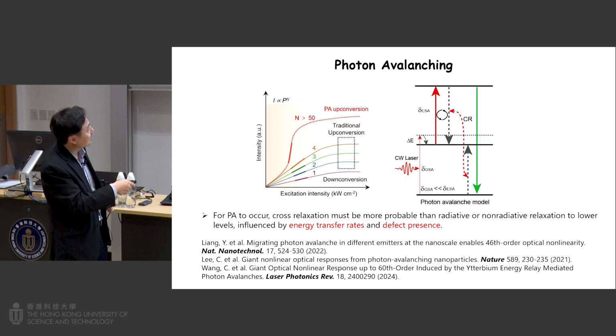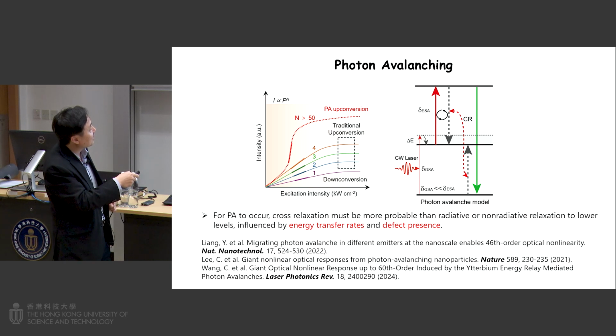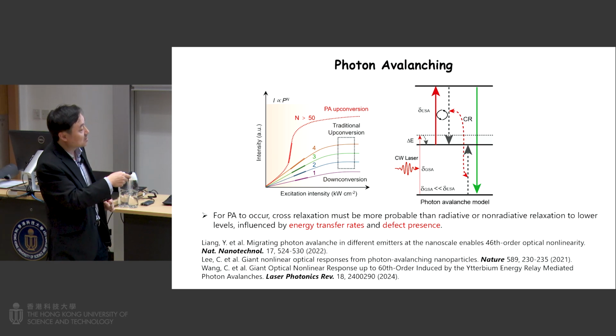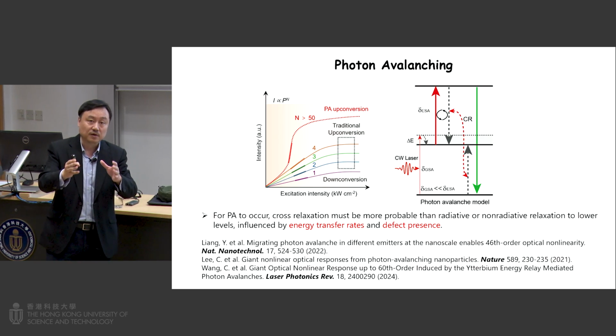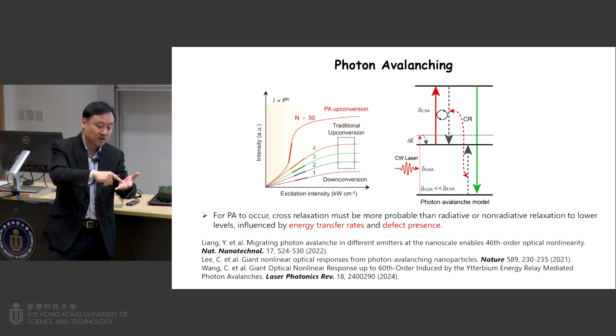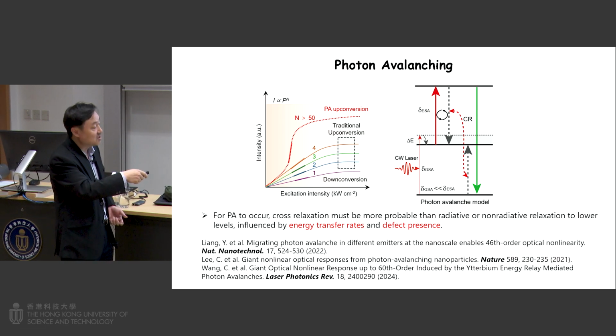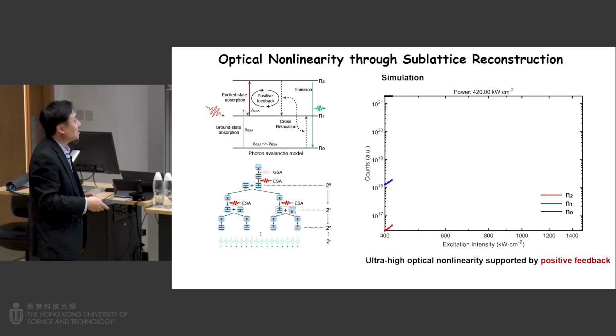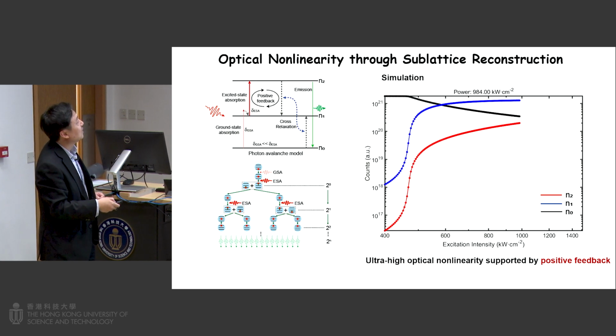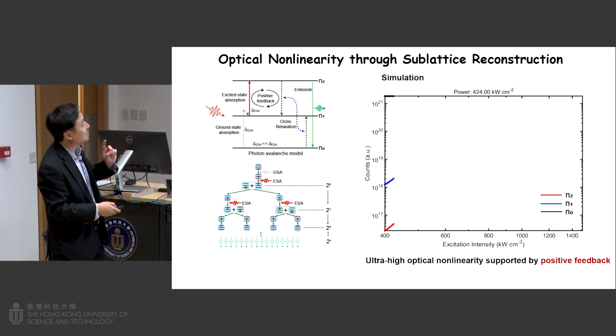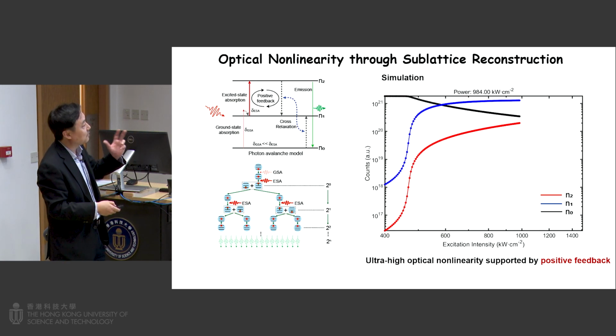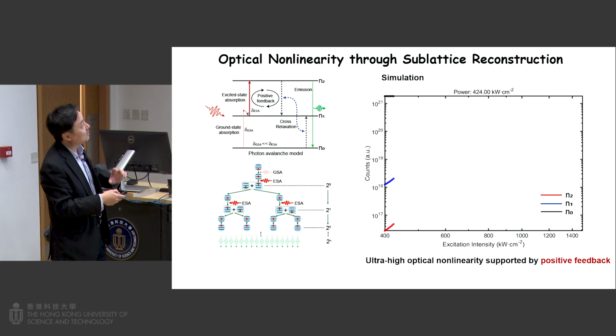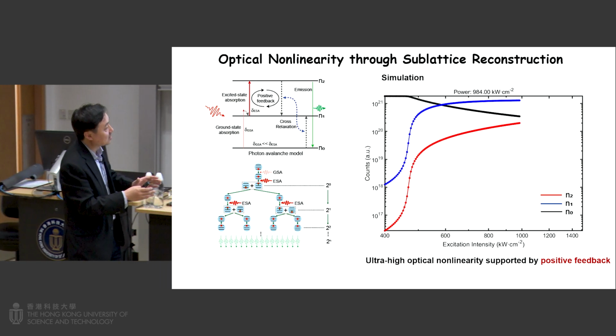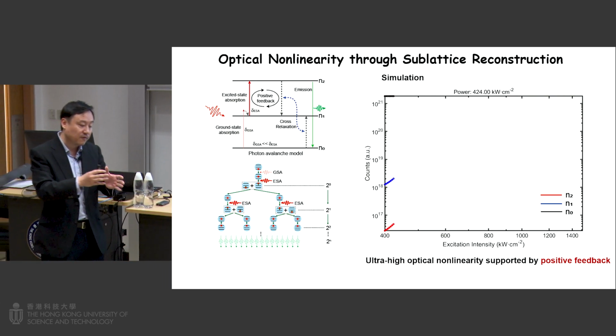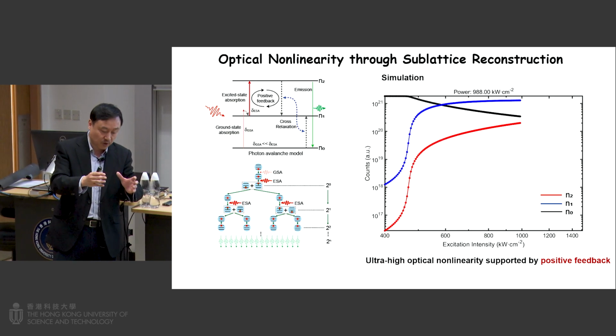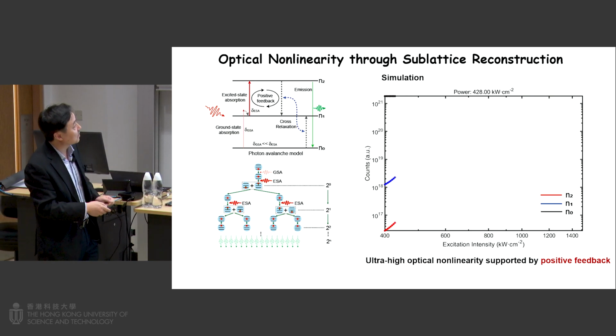So the consequence is, if you can reach very high nonlinearity, you can use this to develop, for example, pressure sensors, force sensors, because the luminescence is very sensitive to the excitation intensity. So I want to give you some examples. This is our recent work. We realized that if we use certain types of lanthanide-hosted materials, we can change the sublattice, the crystal lattice, and modify the crystal field. Once we modify the crystal field, we can significantly enhance optical nonlinearity.